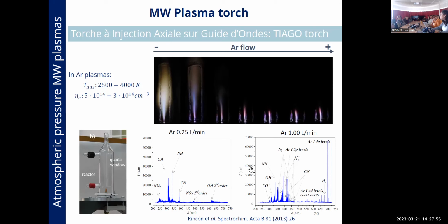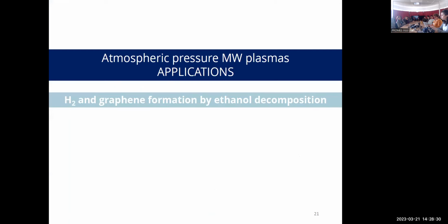If we increase the argon, we are limiting the access of the nitrogen and oxygen into the discharge, and then we can see the argon atomic lines as well as other molecular emissions due to the presence of nitrogen and oxygen. Why am I highlighting this? Because this will be a key feature for the development of hydrogen and graphene production with this torch.